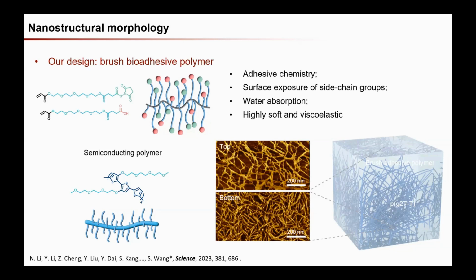The semiconducting polymer on the two surfaces is forming a very dense nanofiber structure with continuous percolation. Basically, this makes sure the transport property, the semiconducting property, is not affected by blending with the bioadhesive polymer. And we have indeed tested in the OECT that the semiconducting property is not sacrificed at all. At the same time, because the bioadhesive polymer serves as an overall matrix, we think this can further enhance the bioadhesive property of this semiconducting layer.